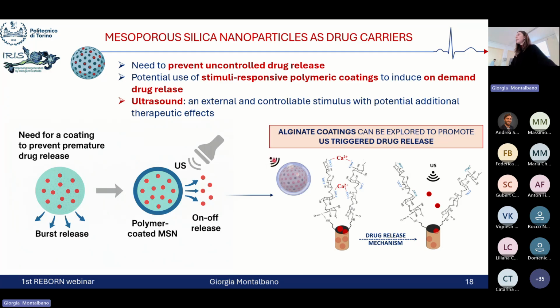So in order to obtain this ultrasound-responsive character, we decided to apply alginate coatings to our mesoporous silica nanoparticles, in order to promote the triggered release of the drug upon application of an ultrasound stimulus that can reversibly weaken the ionic bonds between the polymeric chains, acting as a sort of gate that opens and closes the coating, enabling the release of the drug on demand.